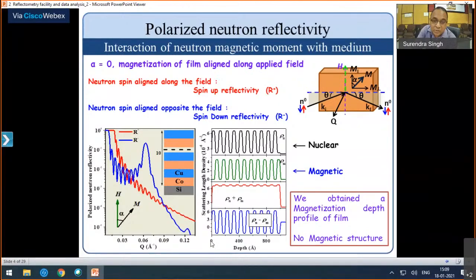Here, as a depth - this is the surface and this is the substrate, the other end. You can see different oscillations for the nuclear part and magnetic part. I have separated these. If you add these two, black and green, you get the red one, and if you add this black and green you will get this blue one. So you can see for R plus, shown as this red curve, the contrast, the density...